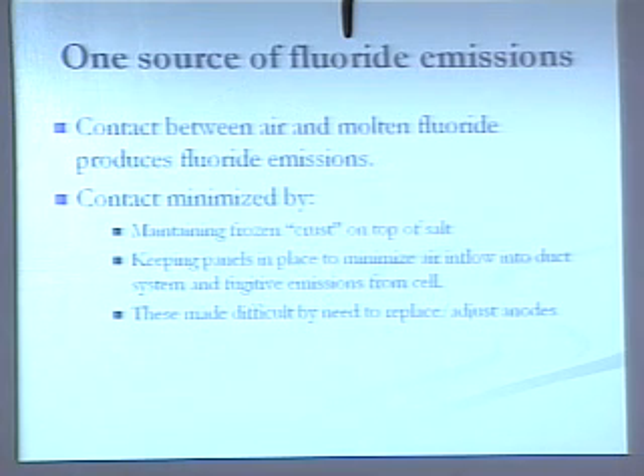Remember these molten fluorides in this cell at 960 degrees Celsius. One source of emissions from the cell, fluoride emissions, is contact between air and the molten fluoride, because air typically contains water vapor that reacts with the molten fluoride, produces hydrogen fluoride, which escapes from the top surface of the cell. And that fluoride generation is minimized by maintaining a frozen crust on the top of the salt. So if you look inside these cells, you don't see molten fluorides. What you see is what's known as an ore cover. It's whitish in color, and it's mostly frozen electrolyte with some of the aluminum oxide, which is fed to the cells, scattered across the top.